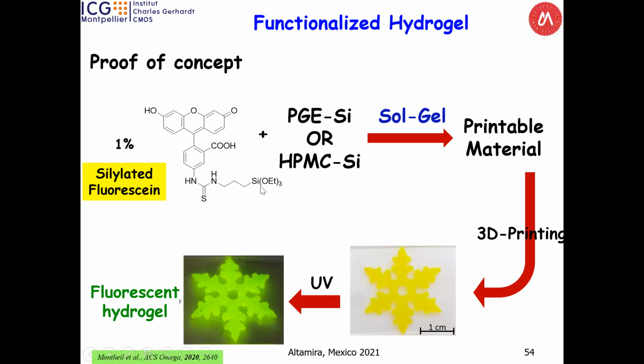Okay. It's just to announce the next step. As proof of concept, we prepared 1% of silylated fluorescein just to be observed under fluorescence microscopy, and we added silylated HPMC or silylated PEG, and we demonstrated that it's possible to make 3D printing. And you can see clearly, even if you are in water, the fluorescein dye remains inside your materials. The idea is for the next step, if this part works.